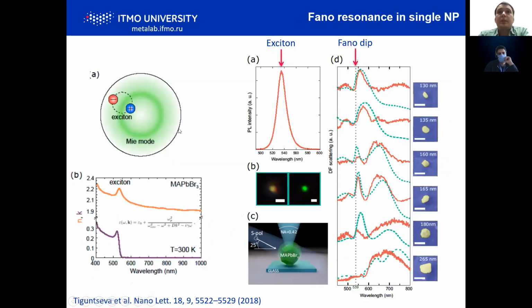Also interestingly, in a Mie-resonant nanoparticle, if we consider the exciton, what happens if we couple the exciton with Mie resonances in the nanoparticle? In this material we also have an exciton, as I told, at room temperature. So we fabricated nanoparticles in this case by laser ablation, and studied scattering properties from each nanoparticle of spherical-like shape.